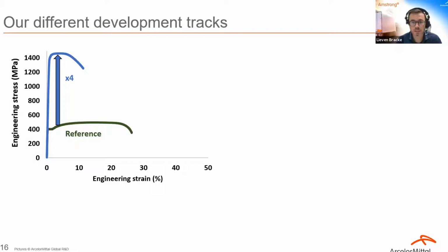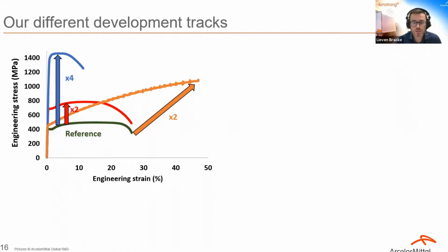And that is also shown in the second development track in the red tensile curve, where we increase the strength with a factor 2, but the formability and ductility is completely maintained compared to the reference. So you can see this steel as a kind of ultimate Armstrong Ultra 700 MC. And then the third group of steels in orange has extreme tensile properties with a yield strength similar to the Armstrong 355 MC, but with a very high elongation and strength after deformation. And this type of mechanical behavior also ensures an extreme wear resistance in tough conditions.